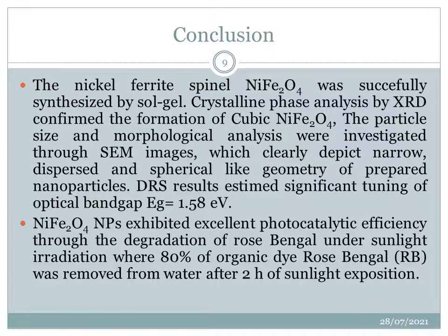The nickel ferrite spinel was successfully synthesized by the sol-gel method. Crystalline phase analysis by XRD diffraction confirmed the formation of the cubic nickel ferrite. The particle size and the morphological analysis were investigated through scanning electron microscopy images, which clearly depict a narrowly dispersed and spherical-like geometry of the prepared nanoparticles.